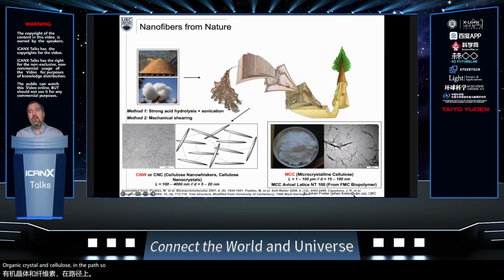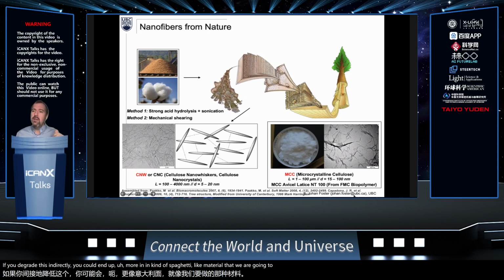So the community has really tried to focus on using cellulose nanocrystals as the term we use. Rod-shaped, from say 100 to a few thousand nanometers long, and say 5 to 20 nanometers wide. So really, think about the shape of a pencil, but in nanoform. There's a wide variety of other sources you can potentially use from this. If you degrade this enzymatically, you could end up more in kind of spaghetti-like material, but we are going to focus on this rod, very stiff-like material.